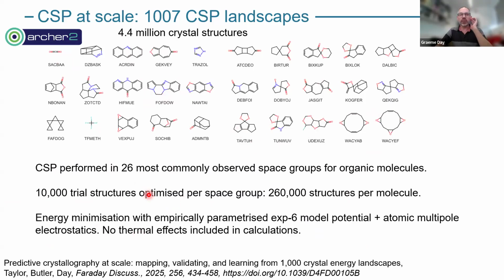So the way Chris did this was he looked at all the most likely space groups for organic molecules. He really wanted to push the convergence of the search, so he did 10,000 structures per space group. So we're up at just over 250,000 structures, energy minimized per molecule. Okay, and he used the force field method to energy optimize these structures.